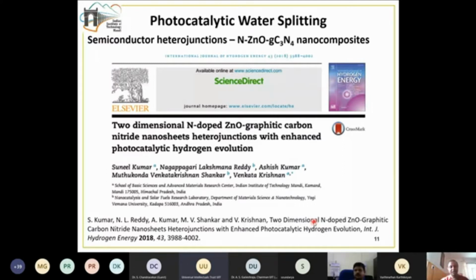And in this case, both are in 2D form, 2-dimensional form. So they can make a face-to-face contact. The 2D can make a face-to-face contact. So there is a much better possibility for this electron transfer. And then we tried again the same photocatalytic hydrogen evolution. And this work was also done by my student, Dr. Suneel Kumar, and it was published in the year 2018 in the International Journal of Hydrogen Energy.